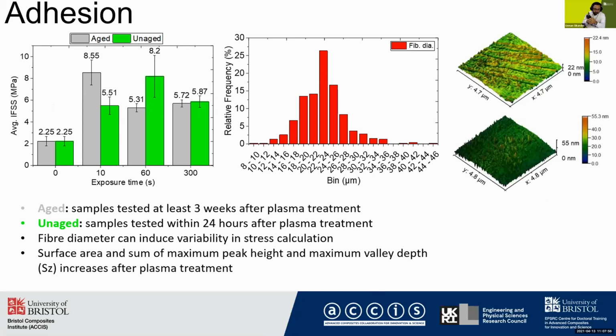We tested two different types of samples, aged samples and unaged samples. Aged samples were the samples that were tested 3 weeks after the plasma treatment, and unaged samples were the samples that were tested right away. And we know that plasma treatment is a temporary treatment. That is why we tested two different types of samples to incorporate the effect of fade away or hydrophobic recovery of the treatment. And we found that in both cases, the adhesion increases. However, the trends for aged and unaged samples are reversed.